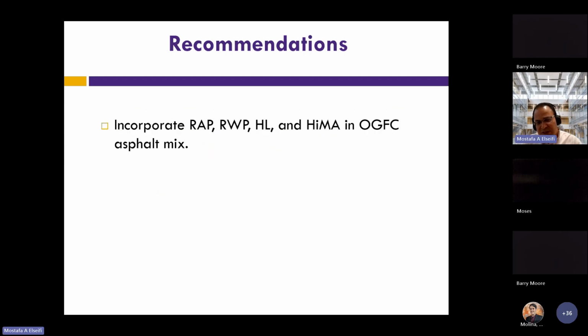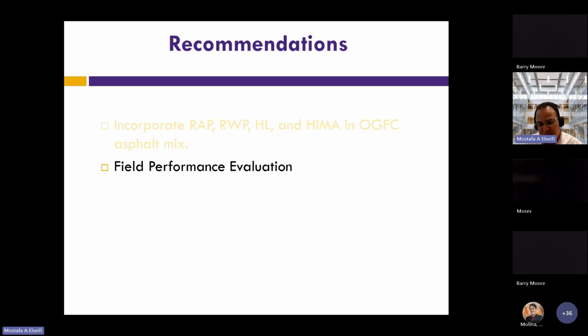In terms of recommendation, we think that we have good confidence in incorporating RAP, recycled waste plastic, hydrated lime, and HiMA in OGFC. And we think that the next step would be the field performance evaluation, so to build some test sections and look at the field performance of these mixes and see how it goes. And if it confirms our laboratory results, that's a very positive sign.